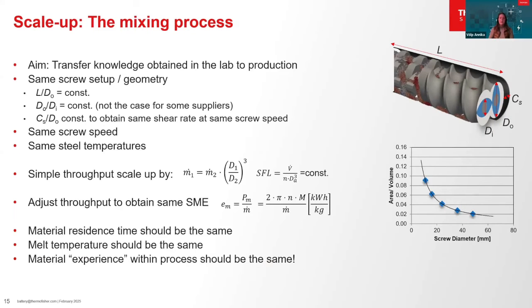We can effectively transfer the knowledge from lab to production, ensuring process consistency and maintaining product quality if we follow some rules. To ensure consistency, we must use the same screw design in both lab and production environments. It is crucial to maintain a constant ratio of the length of the screw, L, to the outer screw diameter, DO, ensuring similar mixing and melting behavior. The ratio of the screw outer to inner diameter should remain constant. It ensures the same filling conditions in the voids of the screws.